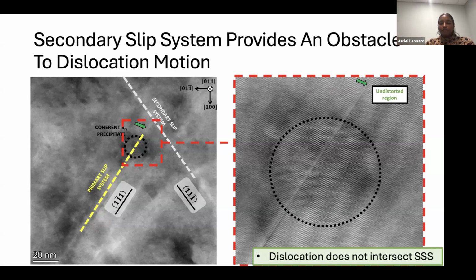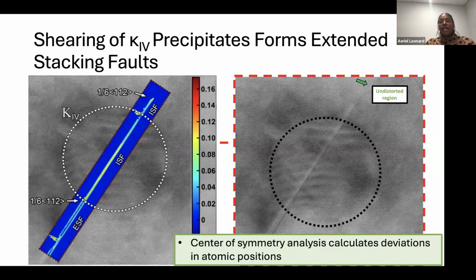Now, if we take a closer look, if you're familiar with center of symmetry analysis, what it's looking at is how the atomic positions are deviating. And so it's calculating this M sub n parameter. The higher that parameter is, the higher the deviation in the atomic positions, which means you have some deviation in the stacking sequence. And the lower that number is, then there is no deviation in the stacking sequence.